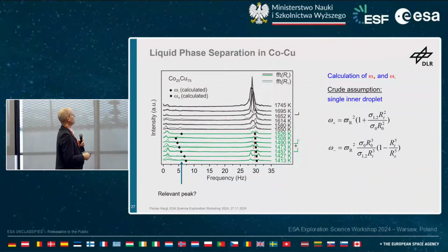So experiments have been carried out on the space station on cobalt-copper, not quite as expected, because the sample undercooled initially quite well during the first cycle, but then had difficulties to undercool later on. We will see shortly perhaps why. From this first measurement, this data was obtained. You see the Fourier transform here, the intensity for different frequencies. So this is exactly looking into the oscillation as a function of temperature.